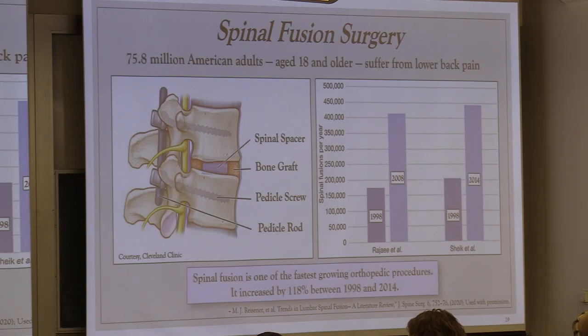Okay, now I want to talk about the other application, which is the one that has been cleared for use, and that's spinal fusion devices. And this is what this looks like in schematic form, or side view. You have two particular vertebrae, and you have in it a diseased or damaged disc or collapsed disc that is excised, and it's replaced with a spinal spacer, which originally was allograft or autograft, and subsequently became allograft, and then became an abiotic material. And you pack bone graft around it, and what you actually do is fuse these two segments together.